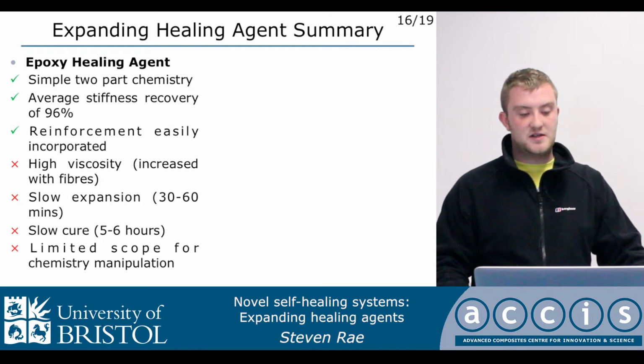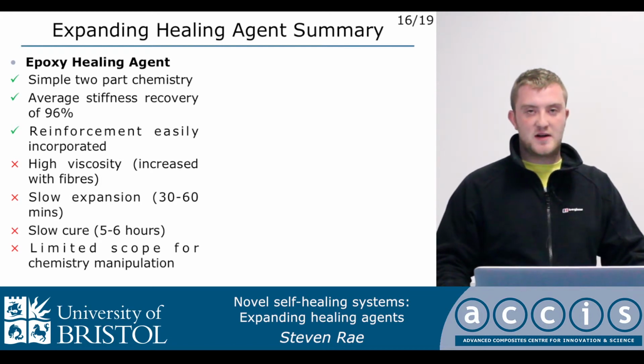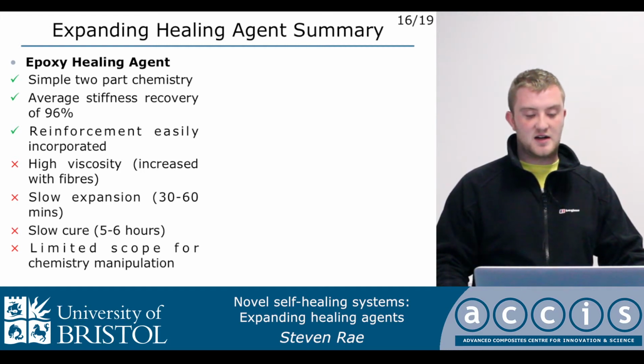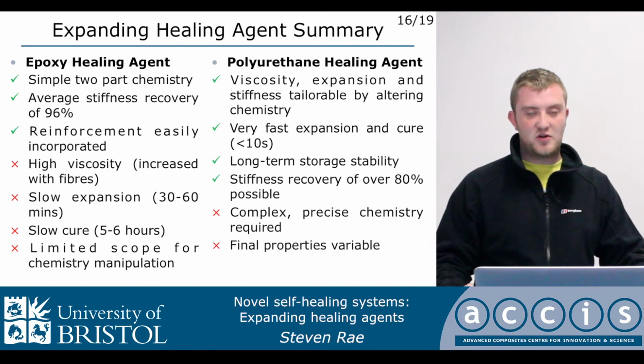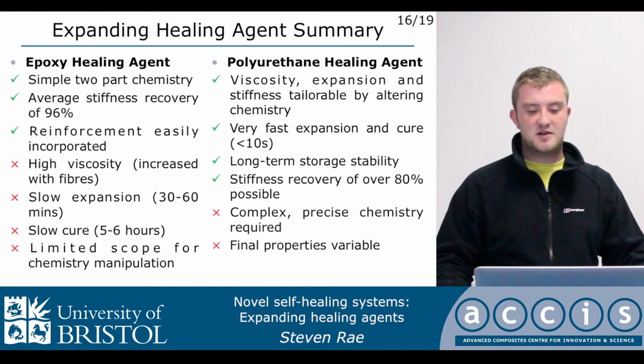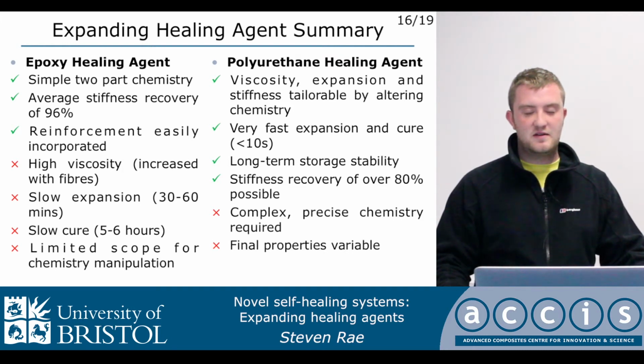So to summarise the two healing agents: the epoxy system is simple two-part chemistry, and we consistently get a high stiffness recovery. We can easily incorporate a reinforcement in there, but it's much higher viscosity and relatively slow to react. With the polyurethane system, it's much more versatile. We can tailor all the properties we want, and it's very fast to expand and cure, but the downside is a bit more complex and precise chemistry is required.